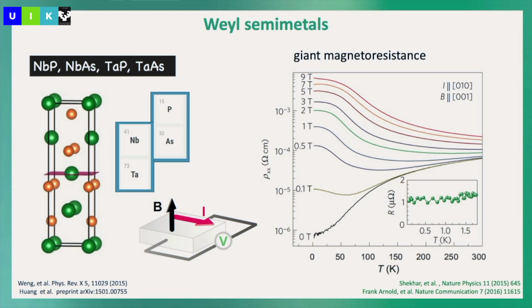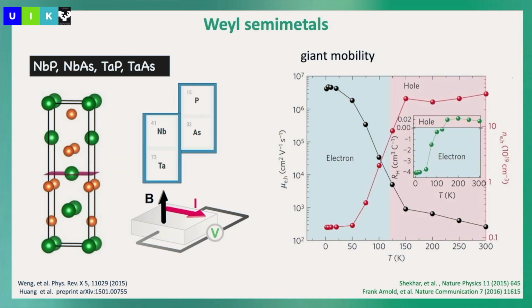So you see responses now, and here you see these nice wiggles, which are the quantum oscillations from which we really can draw the electronic structure of this material. But then if you apply magnetic field, you see it ends always, the electronic structure is like a plateau. So it's also here in the semimetals, the question what happens if you go higher and higher in a magnetic field. But you always see these very giant responses, okay? So you see also mobilities in all this material, which are known for a long time only for gallium arsenide 2-dimensional electron gas, or then graphene, and now there's an inflation of materials. All the semimetals show these very giant mobilities.